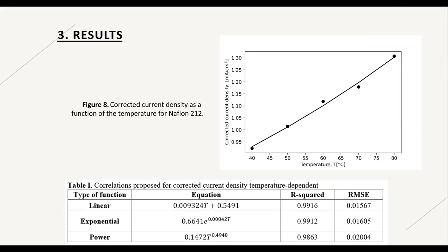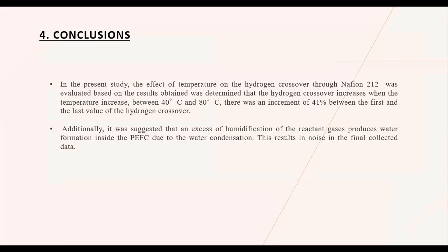In the present study, the effect of the temperature on the hydrogen crossover through Nafion 212 was evaluated. Based on the results obtained, it was determined that the hydrogen crossover increases when the temperature increases. Between 40 and 80 degrees centigrade, there was an increment of 41% between the first and the last value of the hydrogen crossover.